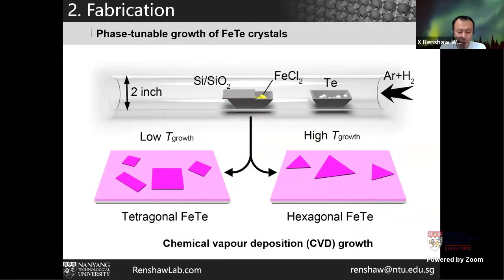So, okay, then talking about the growth, trying to fabricate different structural phases of the materials. CVD is typically a very ideal, affordable, and very quick technique that we can use to check what we can do. The schematic of the CVD is already shown here. Its principle is actually quite simple. You have two gases, you flow these gases, you have these precursors. Eventually, on top of your substrates, which you put into the glass tube or quartz tube, you will be able to get the product.